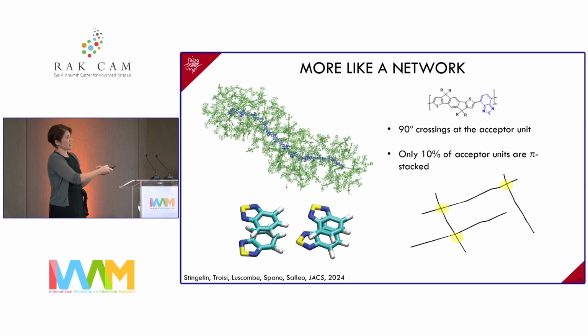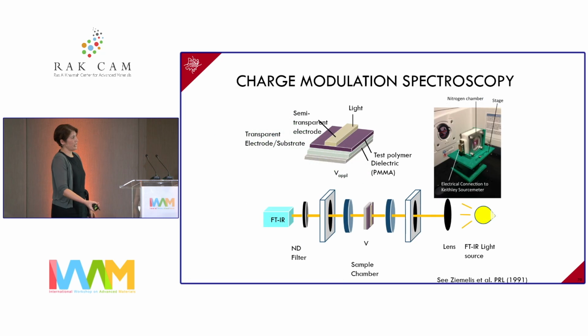And these crossings are not that frequent. It's only 1 in every 10 that has that cross. But that cross is enough that you have fast charge transport along the chain. At the cross, it hops to the next chain, goes fast again. And so you end up with more of this zigzag motion. We wanted to not just, again, imagine this, but to confirm this spectroscopically as well.